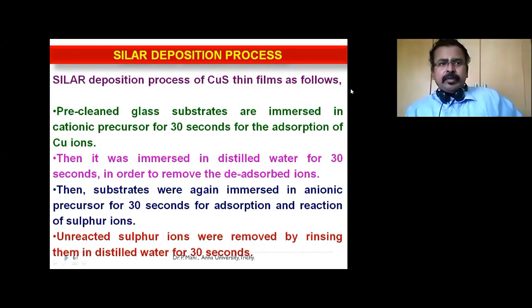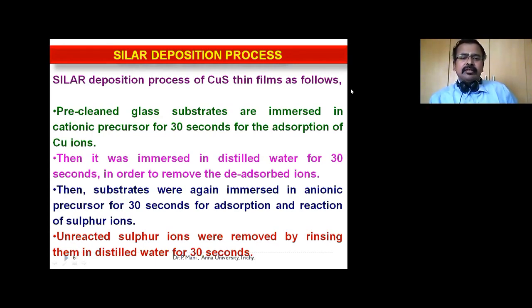Deposition process. In SILAR deposition, we are taking copper sulfide thin films as an example. First, pre-cleaned glass substrates are immersed in cationic precursor for 30 seconds for the adsorption of Cu ions. Then, it was immersed in distilled water for 30 seconds in order to remove the desorbed ions. Then, substrates were again immersed in anionic precursor for 30 seconds for adsorption and reaction of sulfur ions. Unreacted sulfur ions were removed by rinsing them in distilled water for 30 seconds. This is for binary; the same steps are followed for ternary and quaternary.